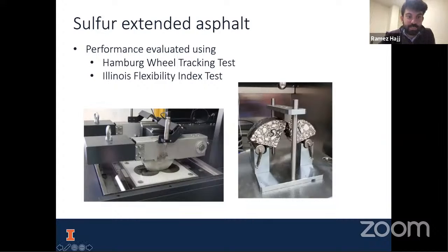This is the Hamburg wheel tracking test and the Illinois flexibility index test, which is also known as the IFIT. So the Hamburg wheel test is a typical rutting test. This test is used basically to apply these big steel wheels to the top of the asphalt mixture, and we check how much permanent deformation occurs in the wheel path. And this is analogous to rutting. Of course, rutting is one of the most unsafe asphalt pavement distresses.